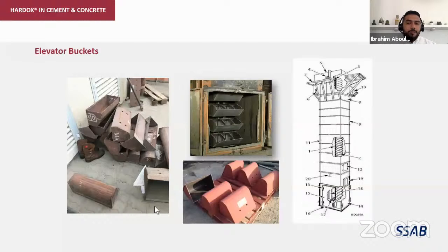The second point, some parts where when you have damaged elevator buckets, the main problem is the cutting edge. And if you have a problem in the cutting edge, you can use Hardox 600 as a strip in the front to improve the wear performance there. So Hardox 450 for the bucket, Hardox 600 for the cutting edge.